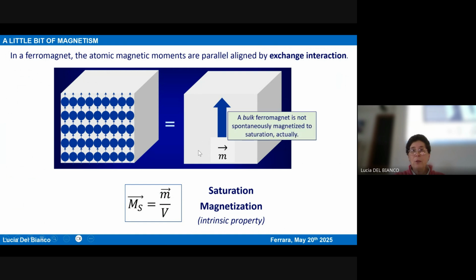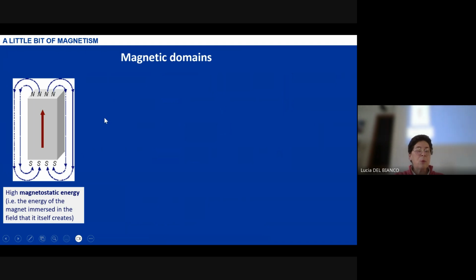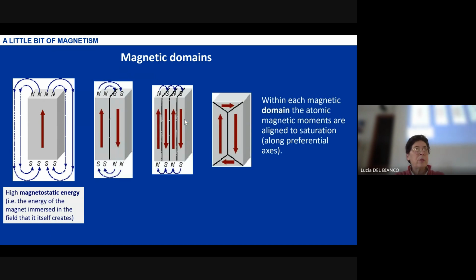Actually, this is not a realistic situation, because if you have a bulk ferromagnet, namely a macroscopic piece of iron, it is never spontaneously magnetized to saturation. And the reason is that if this were the case, your ferromagnet would produce a magnetic field that extends in the space around the ferromagnet itself. But this is not a favorable situation, because in this case you have high magnetostatic energy. And therefore, to reduce the extension of the field and to reduce the magnetostatic energy, a subdivision into magnetic domains appears in your macroscopic piece of iron, let's say.